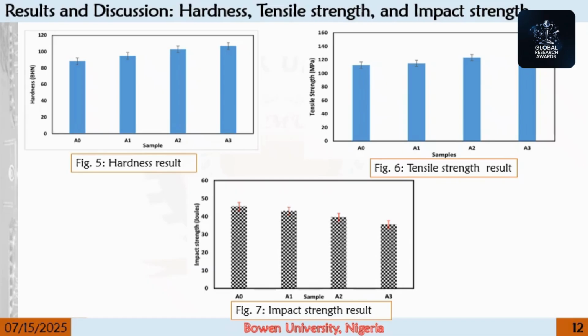Now, for the other mechanical tests, hardness, tensile strength, and impact strength, figure 5, 6, and 7 display them respectively. The hardness and tensile strength of the composite, as seen in figure 5 and figure 6, increase with addition of SDA. This may be due to the presence of hard phase and strengtheners of the SDA particles in the ductile matrix. An increase in hardness can also be attributed to the increasing reinforcement surface area and matrix grain size reduction as a result of addition of the reinforcement particle. And the increase in the tensile strength can be attributed to strong particle and matrix bonding interaction resulting from the uniform dispersion of the SDA particles in the metal matrix.